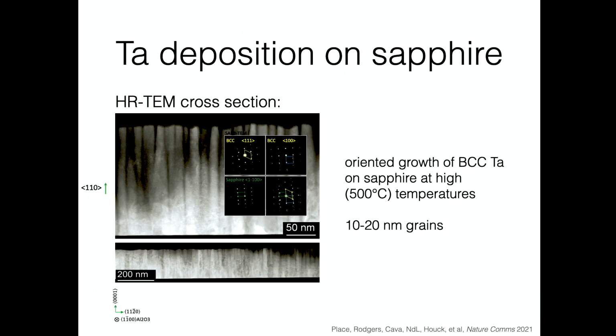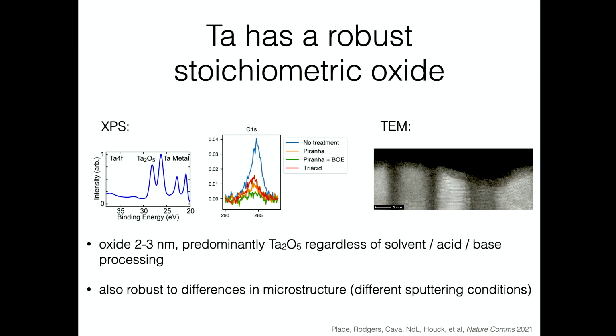So we just went one down on the periodic table to tantalum, which is a superconductor with a critical temperature of something like 4 Kelvin. We can deposit it epitaxially on silicon or on sapphire. And as advertised, it actually does have a very well-behaved oxide. So you always get the same stoichiometry. It's a little bit like aluminum cans never rust because they have a self-limiting oxide. Similarly, tantalum has a self-limiting oxide. So almost no matter what you do, you just have 2 to 3 nanometers of Ta2O5.